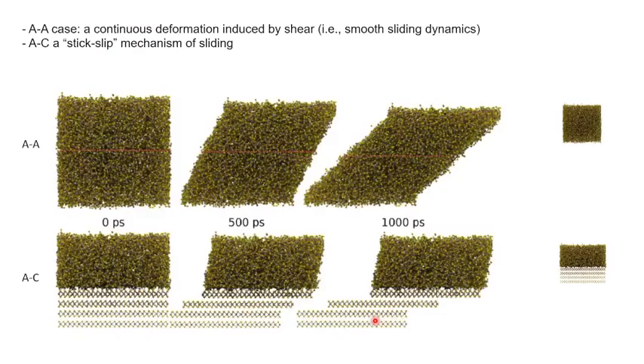The results are reported here, in the case of amorphous on the top part and amorphous crystal in the bottom part. This image represents the beginning of the experiment, so 0 picosecond, after 500 picoseconds, and after 1000 picoseconds. In the case of amorphous coupling, you can see that the sliding of the top part with respect to the lower part only generates a deformation of the structure. While in the case of amorphous crystal coupling, the application of the shearing force induces the slippage of the plane with respect to the others.